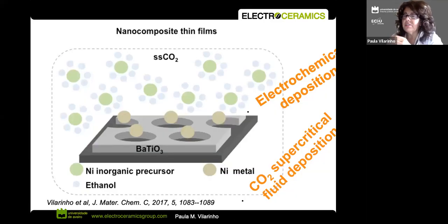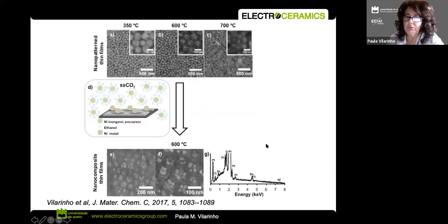So the other thing we decided was, okay, let's fill these small pores with something. And if you look at the image, it's very easy, but in practice, putting some small particles within these very small holes is much more difficult than playing golf. And maybe those of you that know golf know it's not easy, but putting these particles inside of the holes as films, it's like a nightmare. So we use supercritical fluid deposition. We collaborate with a Spanish group.